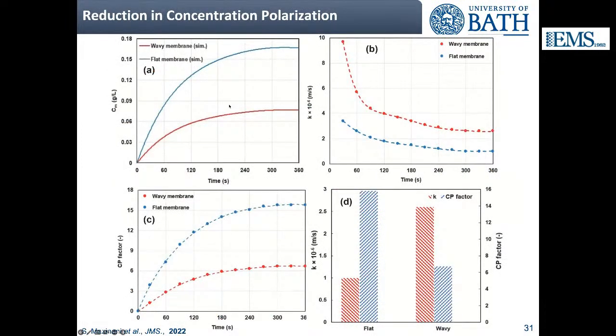So what we then did is to look at both charged dyes and salts and look at concentration polarization. So here you have 4 plots. Let's actually start from the top two. The top two relate to mass transfer resistance. The red curves are all for the wavy membrane, and the blue curves are for the flat membrane. And in general, you see that the wavy membrane has better transport properties than the flat membrane.